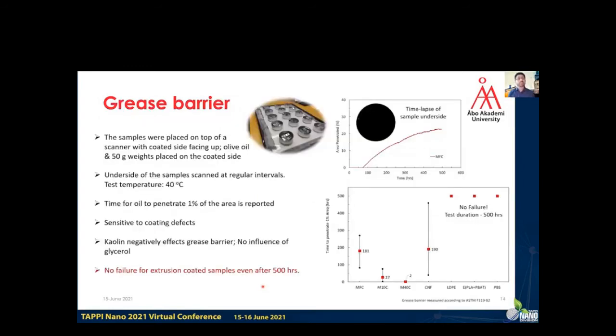Moving on to grease barrier. We used olive oil as the grease test, and this was done at 40 degrees Celsius. Traditionally, grease barrier is tested by putting the samples on a glass plate and observing at regular intervals whether the oil passed through or not. But this can be very challenging, especially when you have white paper and need to see oil spots on the bottom of the paper.